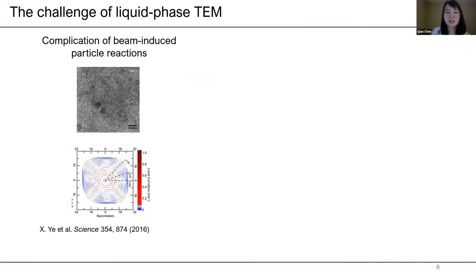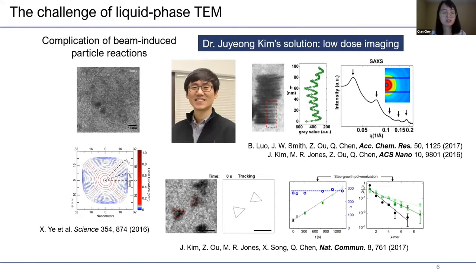This is a challenge first recognized by my postdoc, Dr. Juyeong Kim. The first few papers he published with us were really trying to push the electron beam intensity to be as low as possible in liquid phase TEM imaging. At this very low electron beam intensity, he was able to completely eliminate the beam-induced nanoparticle reactions and heating effects so that he could observe this nanoparticle self-assembly dynamics shown here.